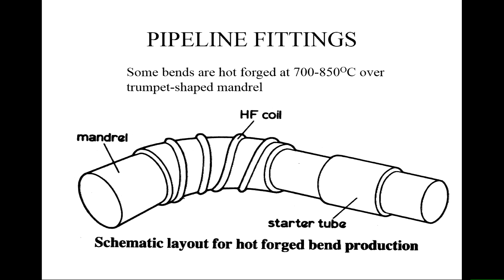The mandrel inside prevents the tube from collapsing as you bend it. I mean, if you take a tube and bend it like this, you tend to find you're stretching the outside and compressing the inside. And the inside of the curve which you're compressing can buckle, it can ripple. And the outside can stretch and break. So you've got to control the process so that you don't damage either side of the tube. And having an internal mandrel helps that. Those of you who've done any plumbing know that a pipe bender for copper pipe at low temperatures has a little steel spring that you put in the middle of the pipe when you bend it to stop this from happening. So this elastic buckling has to be prevented even in these high temperature processes.